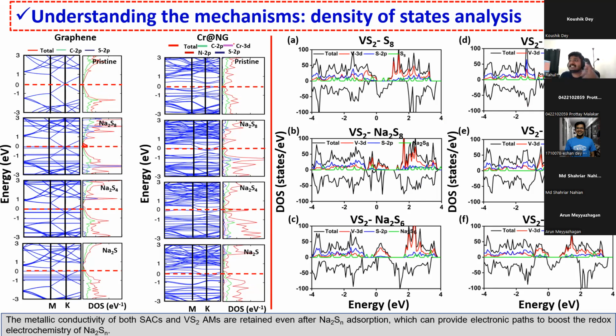Now, when we talk about the single atom catalyst, even before the polysulfide, just the pristine single atom catalyst, if you run a band calculation, we found that the single atom catalyst itself is conductive in nature. That means it can conduct the electrons between the bands. Now, even after the polysulfide adsorption, even after Na2S8 adsorption, Na2S4 adsorption, Na2S adsorption, you can see that there are states at the Fermi level. That clearly indicates that even after the polysulfide adsorption, the conductivity is retained. There's no problem with the conductivity.